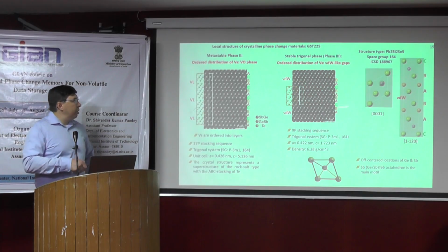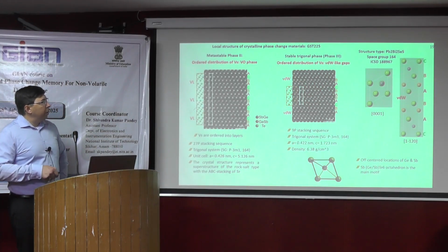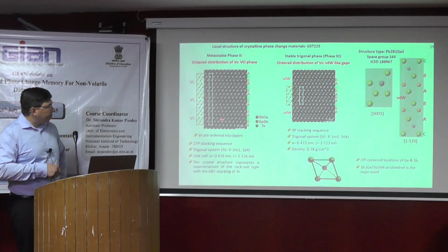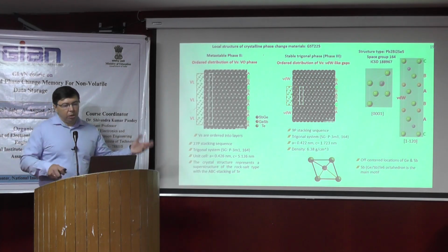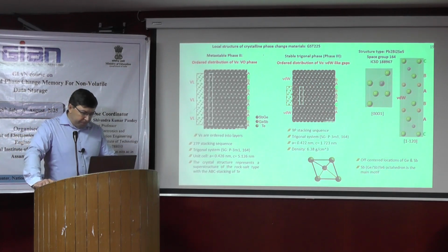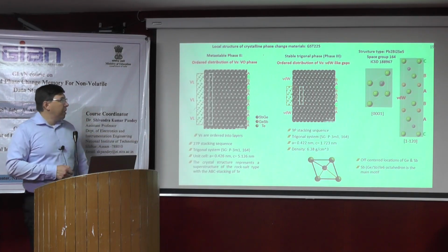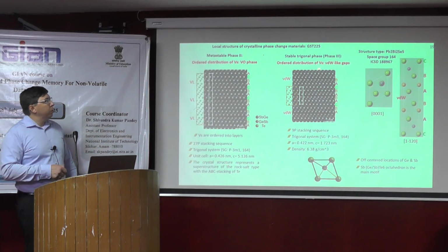Structurally they are very similar in the sense of building blocks, the structure of building units. Here we also have antimony-rich layers close to the so-called van der Waals gaps in this phase. But these are not really van der Waals gaps, as you know from graphene, for example, or graphite. Here the distances are smaller, and they also represent vacancy layers. To distinguish between these two phases, we will call them van der Waals-like gaps.